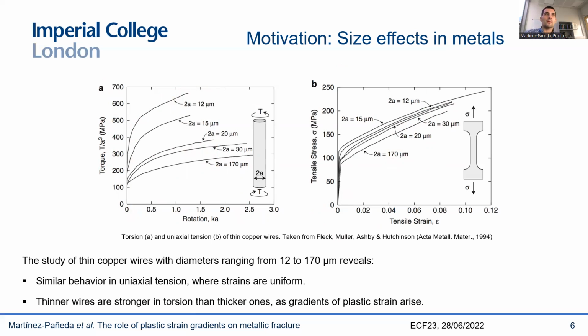And this is quite remarkable because these are, again, normalized curves, kind of stress, equivalent stress strain curves. So there's quite a significant size effect that you cannot capture with conventional theory, right? So in a way, that is the critical observation, that whenever you have homogeneous strain distribution, like you have in uniaxial tension, so no gradients of plastic strain, then there's no stress elevation. However, whenever you introduce gradients of plastic strain, geometrically necessary dislocations, then you get a very significant stress elevation associated with these plastic strain gradients.